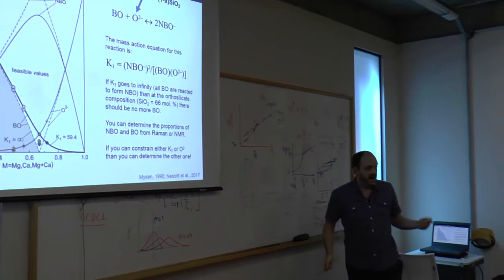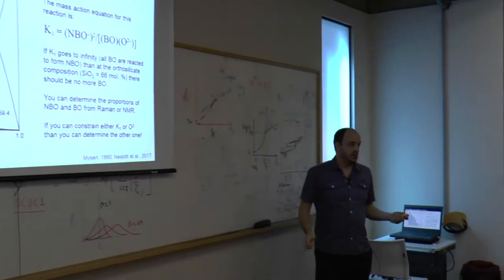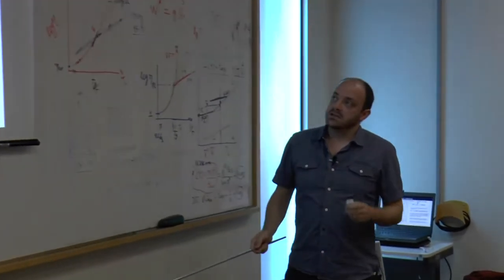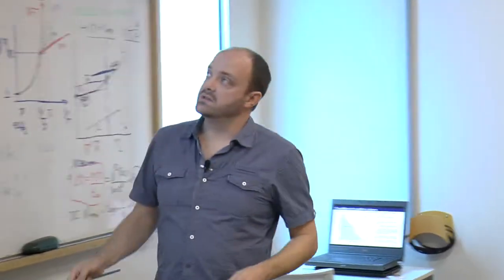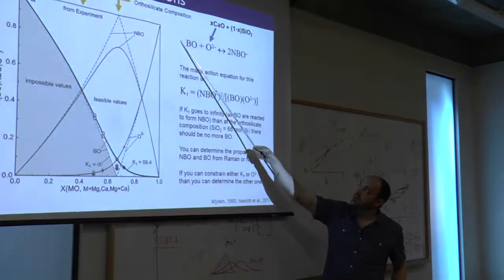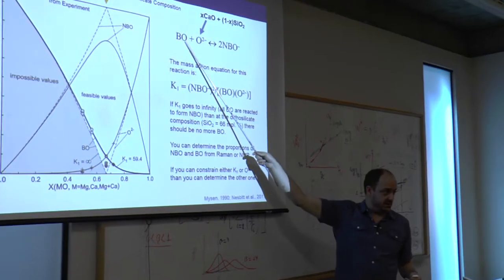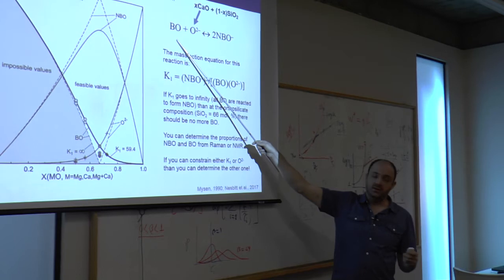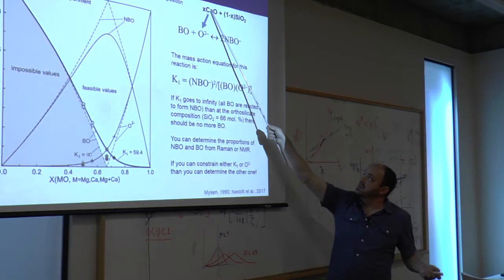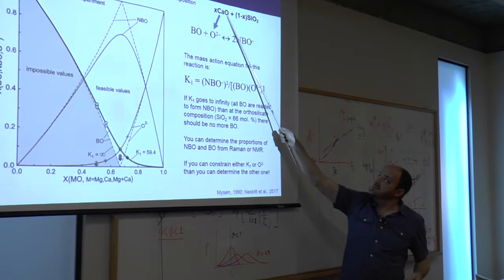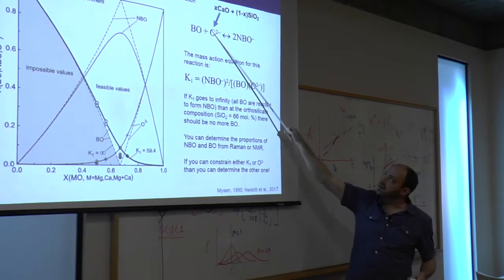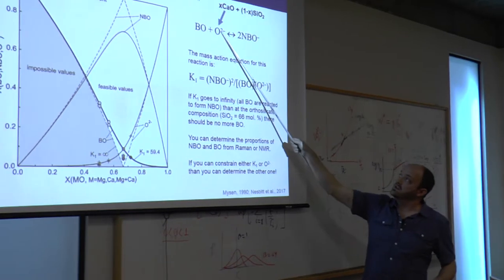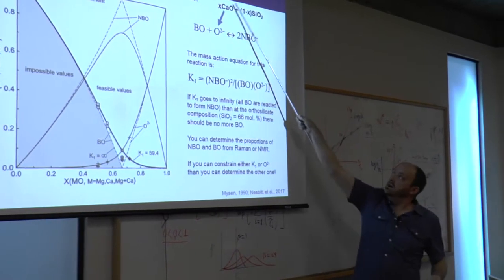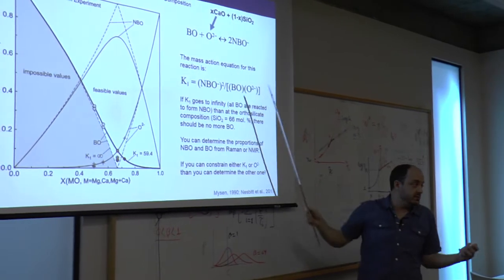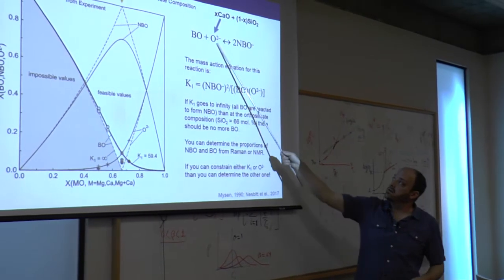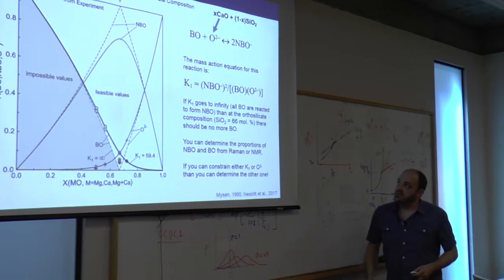What has to actually happen when you add these modifiers to the network? This is quite important in how you view the system. If you have pure silica that only has bridging oxygens in it, where every tetrahedron is connected to another tetrahedron, and you add some modifier, for example calcium, with that calcium comes an oxygen, and this is the sort of free oxygen that those guys are talking about. So it's not totally free in the network. It's bound initially to this calcium, but then it reacts at high temperature when you melt the system together, and you have to produce non-bridging oxygens in the process.